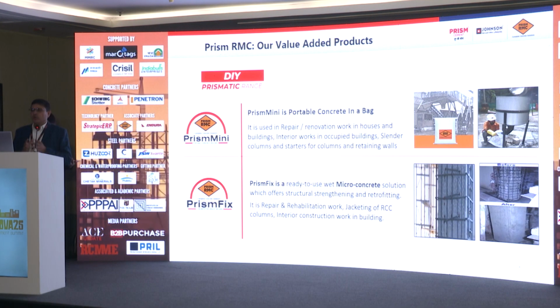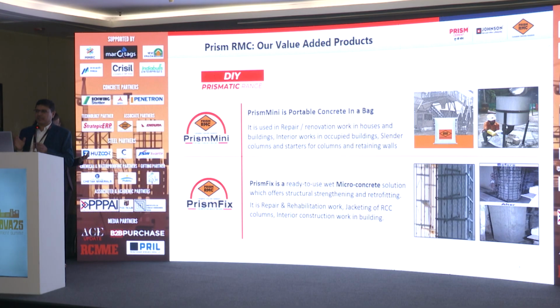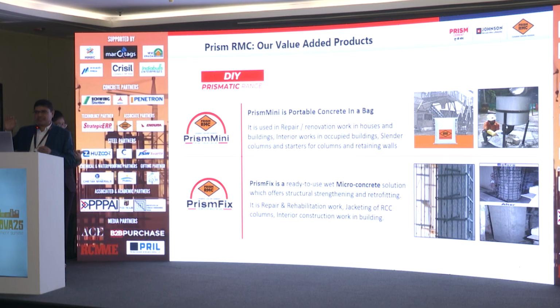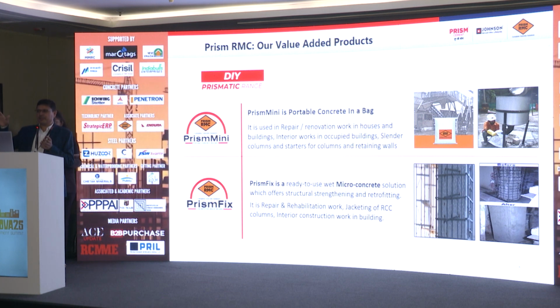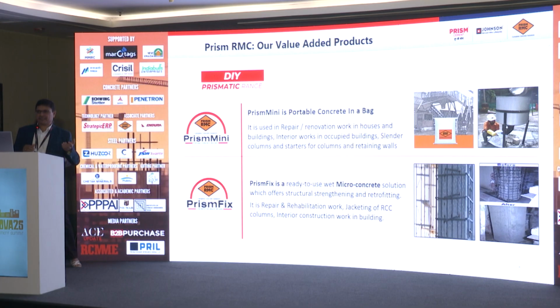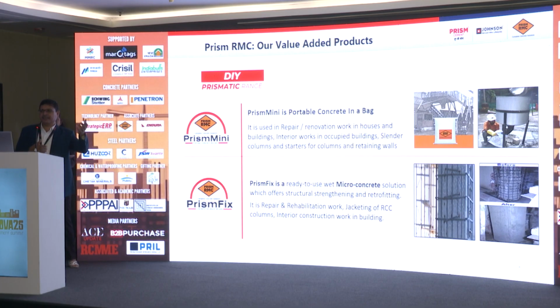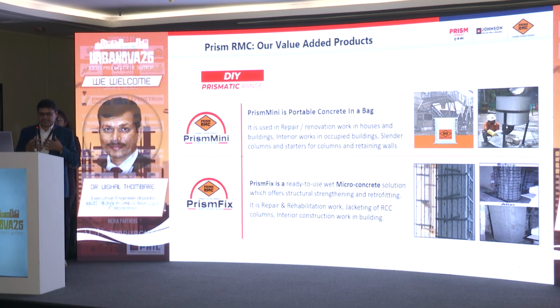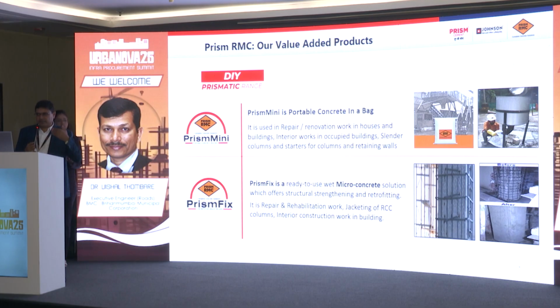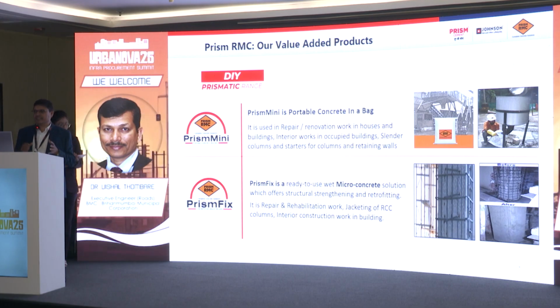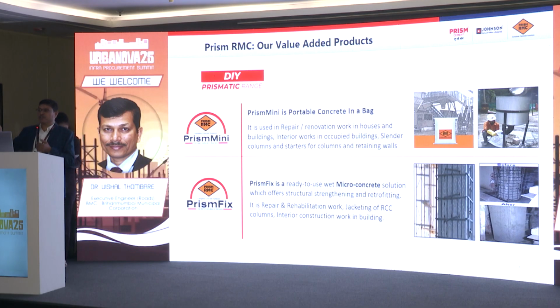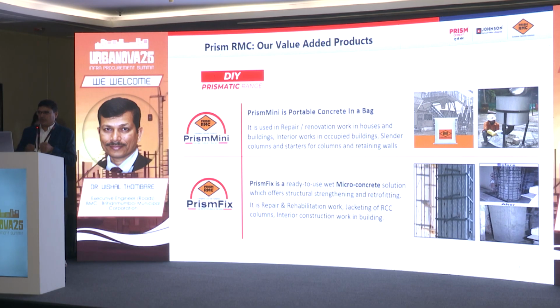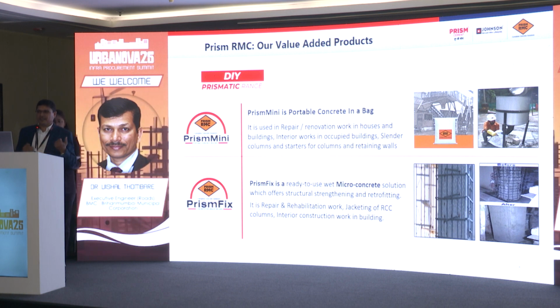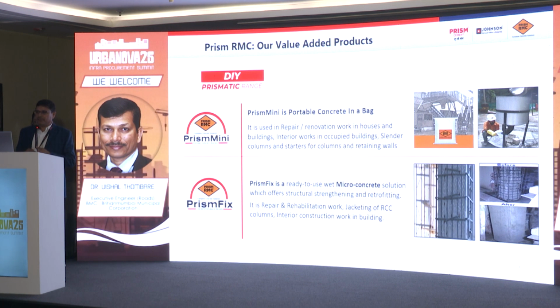We actually supply concrete in transit mixers of 6 to 7 cubic meters, but in some places where the transit mixer cannot go, or when the quantity of concrete is very small, 0.5 to 1 cubic meter, we have developed concrete which can be supplied in bags. Normal concrete cannot be supplied like this because it gets segregated and bleeds, but we have developed concrete in such a way that it binds together, and even after traveling 1.5 or 2 hours, it doesn't get segregated, and it can be used up to 4 to 6 hours. So we get fresh concrete properties with no additions required at site. We only need to open the bag and place the concrete. We have recently developed this concrete and supplied many customers.